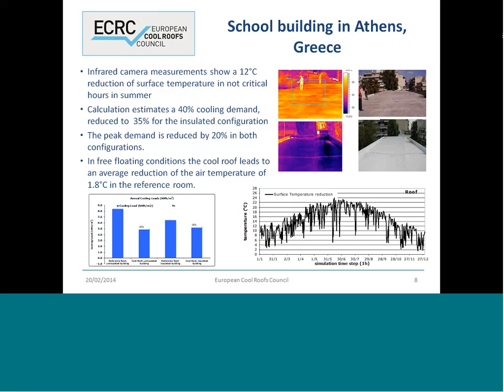The calculation results that are summarized in this graph show a 40% cooling energy savings for the actual building. The simulations were also run considering the building thermally insulated, and the cooling savings were in this case about 35%. Another relevant result was the 20% reduction of peak load, which means downsizing the chiller with consequent cost savings. The calculations were also carried out in free floating condition, resulting in an average temperature reduction of 1.8 degrees in a reference classroom below the roof.